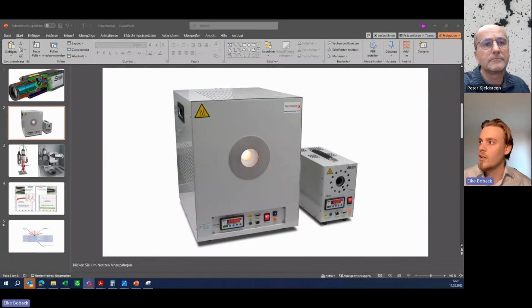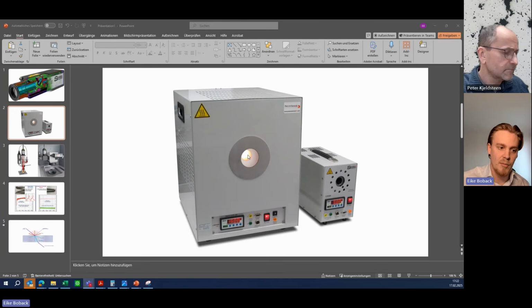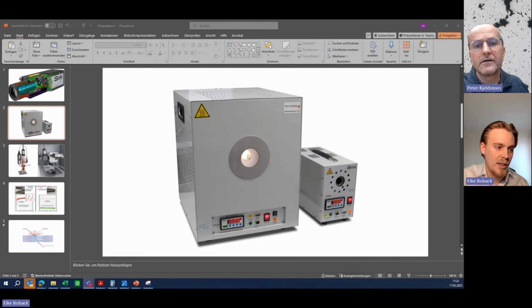Now you could see the thing. This is like the heat source I mentioned. If you look inside it, you have nearly 100%. It's not possible exactly 100%, but nearly. So that's the point where you can calibrate the pyrometer over this Planck curve, it's called. Okay. And then you only adjust it with the emissivity factor you can put in the pyrometer. Aha. Yes.